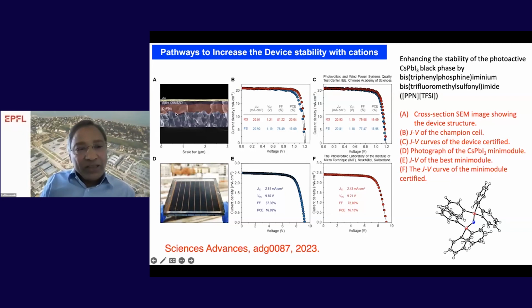So if you look at this, CsPbI3 has a 1.7 eV band gap, and the VOC is 1.21 V, and the resulting power conversion efficiency is 20.64%. So this is a smaller cell area. And here is the certified efficiency of the same cell, which is close to 19.7%. And we made modules using the same configuration, same material, and the efficiency is around 17% in the lab, certified at 16.1% efficiency.